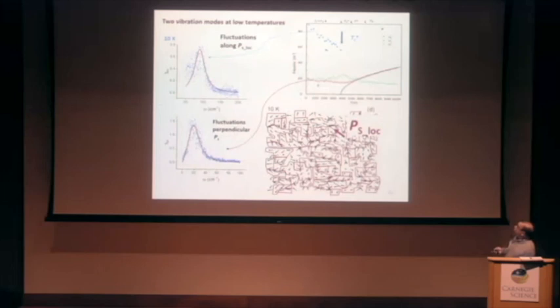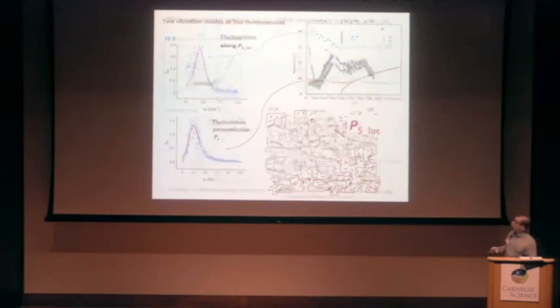But if it is a phase transition, a local phase transition, spontaneous polarization should appear in polar nanoregions or polar nanodomains, and this should give rise to the lowering of symmetry as described in the previous presentation. What we did, we calculated the response inside the polar nanoregions. We used polar nanoregions of about 30 perovskite unit cells, and calculated the response perpendicular and parallel to spontaneous polarization inside this polar nanoregion, and see that this high-frequency mode is exactly the fluctuation along local polarizations, and this mode is the fluctuation perpendicular to local polarization.